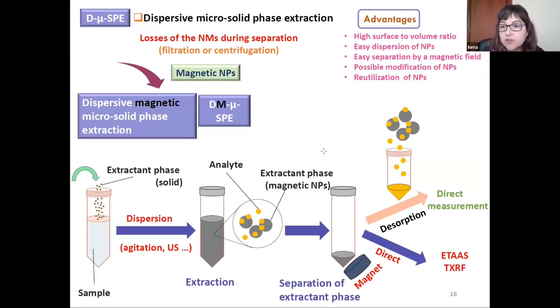Mainly, if the desorption is complete, we can reuse the magnetite nanoparticles for other extractions, if they are also not damaged during the desorption step. In the slide, we can see the scheme of the procedure developed.